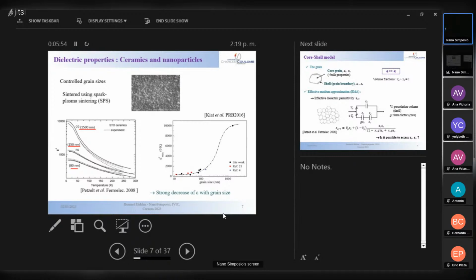You see that the dielectric constant decreases. So this lowers the capacity of these materials for their application. And if you look at this graph, in abscissa you have the grain size, and here you have the permittivity, and you see that you have a strong decrease of the dielectric constant when you reduce the grain size.